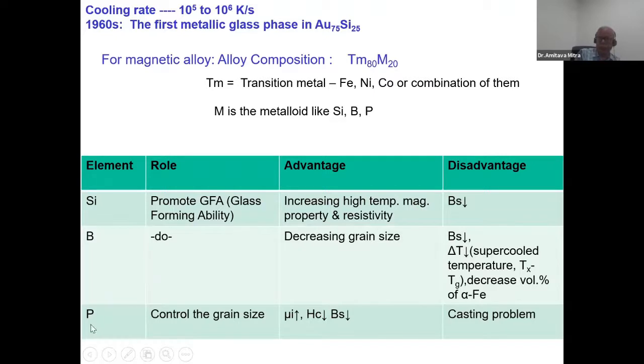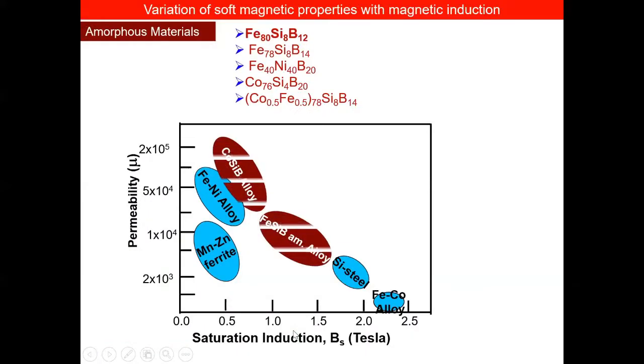And if you have high phosphorus, then the casting, in the form of ribbon, will be very, very brittle. But it has an advantage actually - the permeability is high and the coercivity is low. That is an advantage of adding phosphorus.